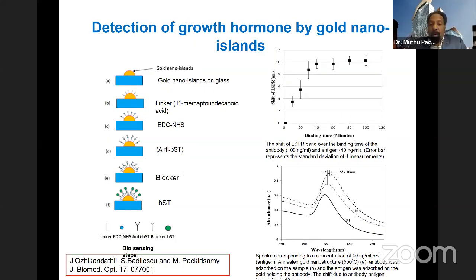One of the good examples, as I told you, is the growth hormones. We developed these bioprotocols. Essentially, the growth hormones, the BSTs, act like antigens, and we use antibodies for them. Then we use antigen-antibody interactions to detect them. That's a typical way that we did it. But in this one, what you see is the plasmonic shift, basically the localized surface plasmonic shift of these nanoparticles due to these antigen-antibody interactions.